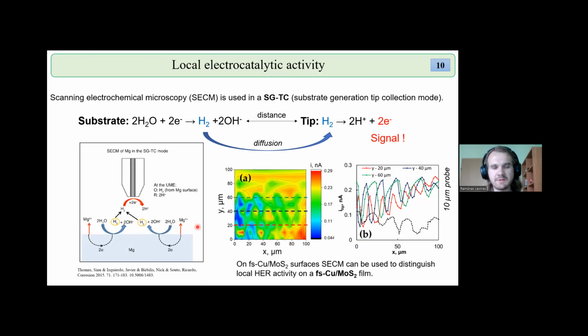And in this way, the probe is moved across the surface. We obtain 2D heat maps. And although these maps are not particularly expressive, the 2D slices very clearly show that the tip does register the surface morphology. This dotted line is shown from a profilogram of identical dimensions in micrometers. And the hydrogen evolution reaction activity does follow this profilogram. So in this way, we can measure differences in local hydrogen evolution reaction electrocatalytic activity.